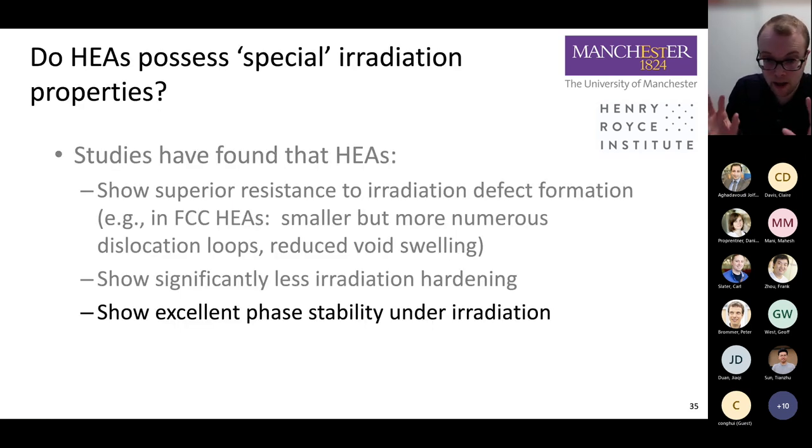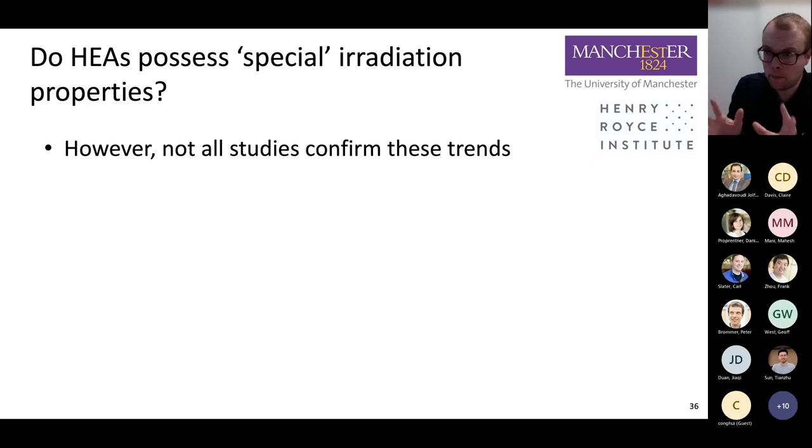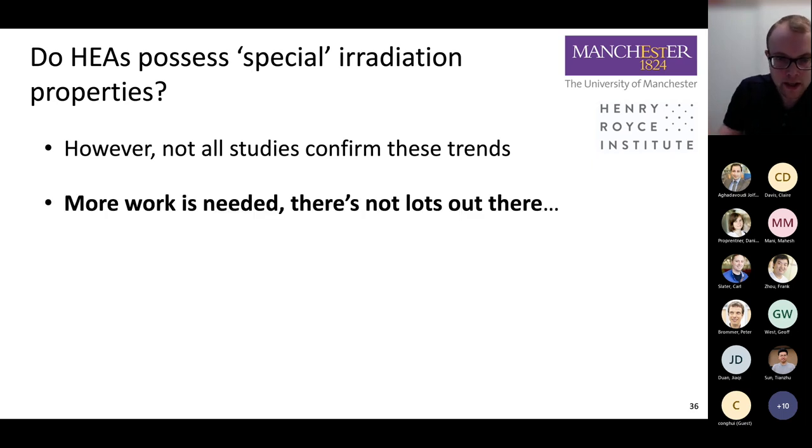There have also been some claims, and there were some studies that demonstrate this, that some high-entropy alloys possess excellent phase stability as well under irradiation. So we irradiate them at temperature and they don't seem to decompose as readily as other alloys. Okay. The problem is that we can't talk about this in general terms, because not all the studies confirm these trends. Some studies, for instance, have found that they aren't stable, you know, they don't show great phase stability when irradiated.